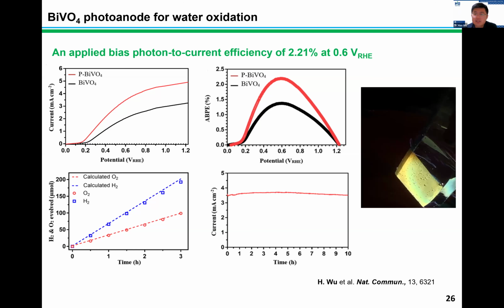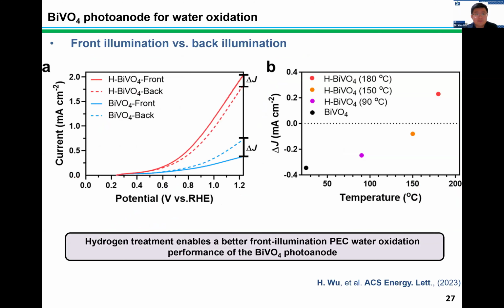To understand the interaction between the oxygen vacancies and the small polaron, we introduced hydrogen doping or substitution of bismuth vanadate, which substitutes the oxygen vacancies of bismuth vanadate, passivates the bismuth vanadate with the oxygen vacancy defects, and induces a much improved performance. In particular, it achieves a better front illumination performance compared to the back.